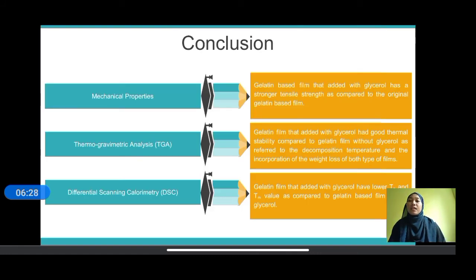Okay, so next, as per the conclusion, we can say that the gelatin-based film added with glycerol has a stronger tensile strength as compared to the original gelatin-based film. The gelatin film added with glycerol had good thermal stability compared to the gelatin film without glycerol, as referred to the decomposition temperature and the weight loss of both types of film.